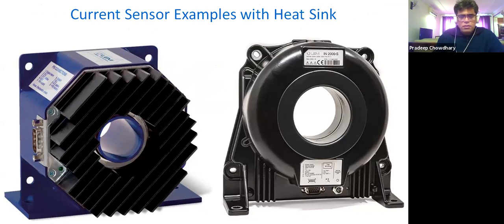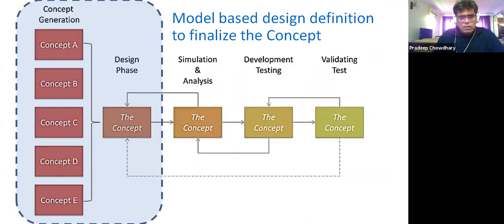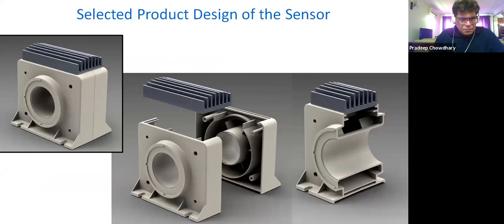The one that has been taken as a case for this presentation starts with the concept, and a design was done. I will not get into the details of that, but show you what the concept looked like. So a current sensor was developed here, and it met all criteria. Heat sink was designed to extract the heat out, where the PCB board was on the underneath of the heat sink with the MOSFETs reaching temperatures almost up to 178 degrees. But the housing had to be not in contact with that temperature. It was a heat sink, and the housing was coming to approximately 120, 121 internal heat in passive situation. So we're not talking about the outside, we're talking about the inside. So in this case, we met all the requirements and the product was developed meeting clients' expectations, or so we thought.